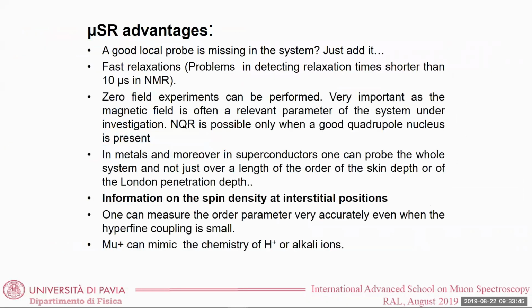Another relevant complementarity of μSR with respect to other techniques is that, in most cases, you have a mu plus which goes in interstitial position, okay? And, for example, if you probe the muon shift of the mu plus in interstitial position, this shift is related to the amplitude of the electronic wave function at this interstitial position. While with the nucleus, you probe the amplitude of the electronic wave function at the nuclear site. So there is also this site complementarity between nuclei and muons.